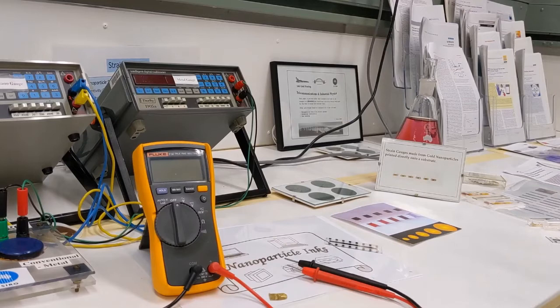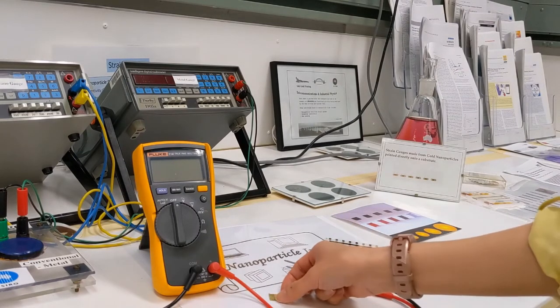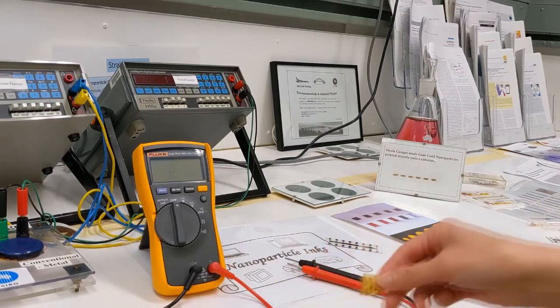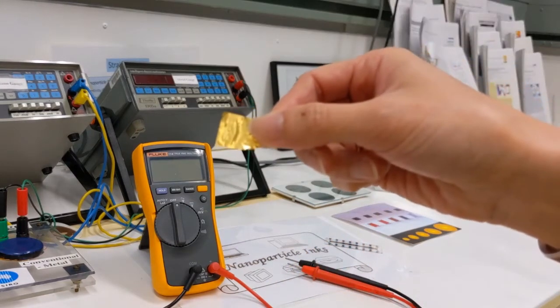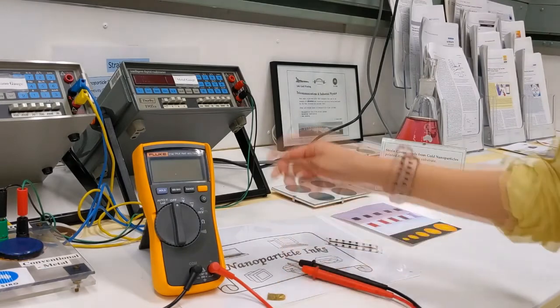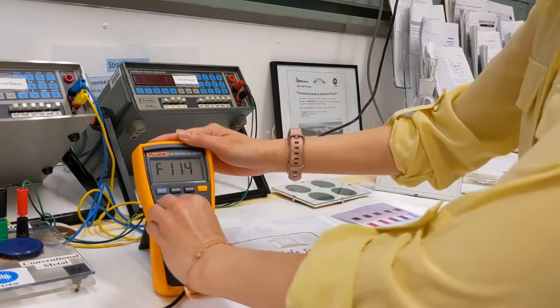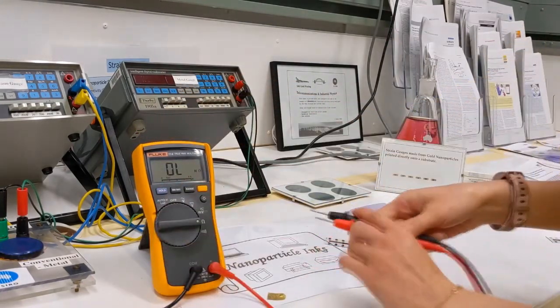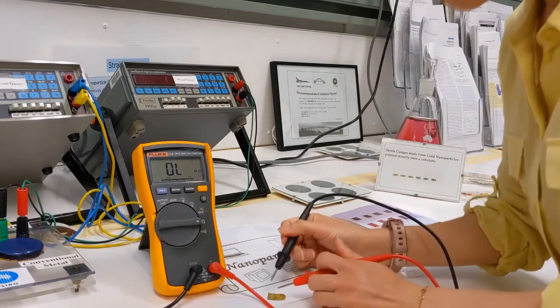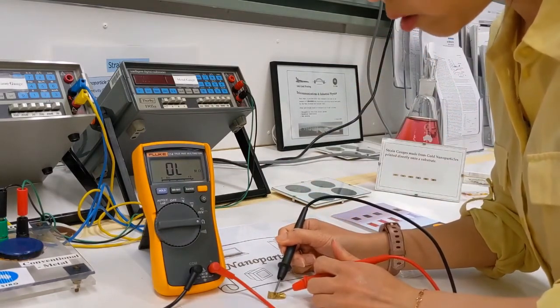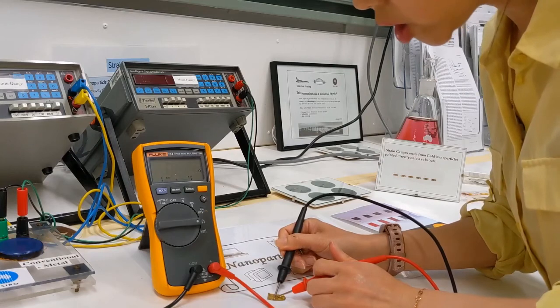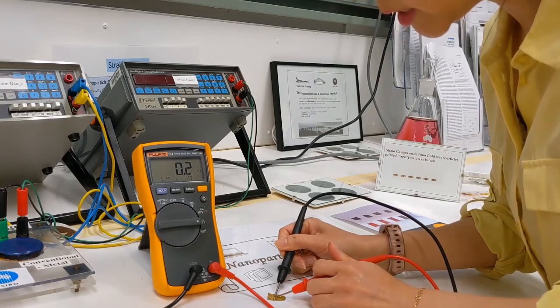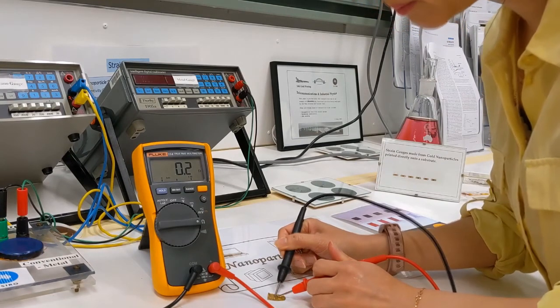Now let me show you the differences between gold nanoparticles and bulk gold. Now this here is just a regular sheet of gold foil. Now if I were to measure the electrical resistance using a multimeter, you'll see that the gold foil is actually quite conductive. It shows very low resistance, 0.2 ohms.